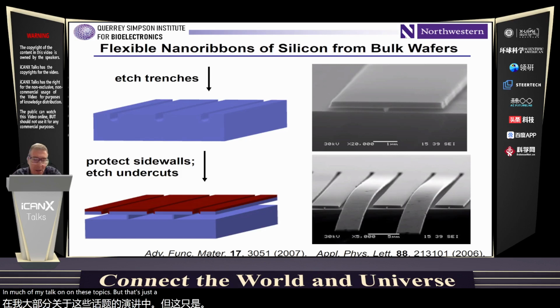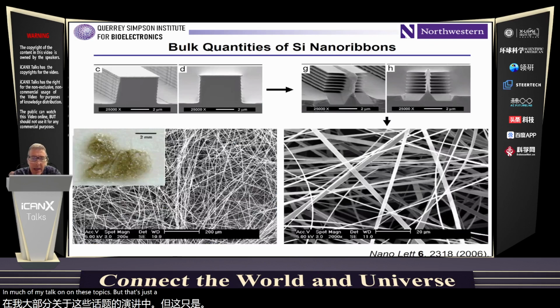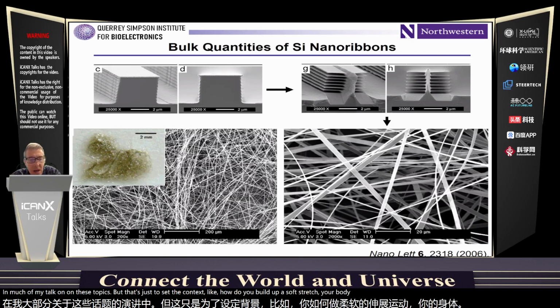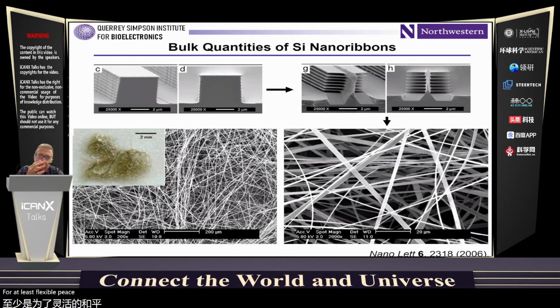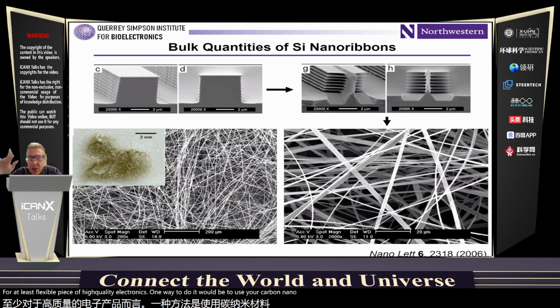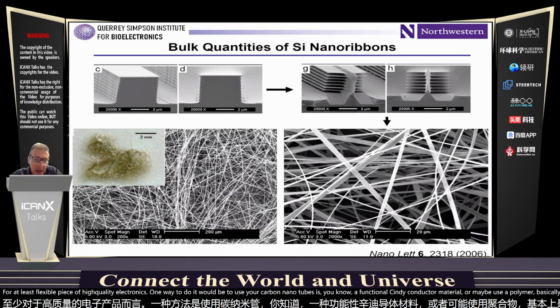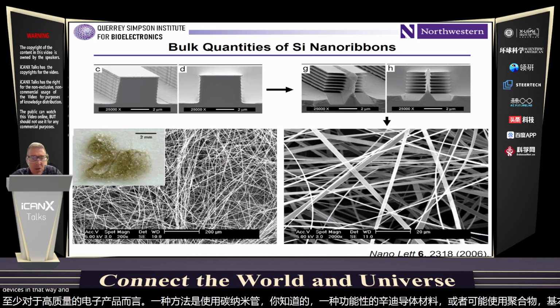And you can work your way down through the thickness of a wafer in a serial sequential set of etching processes, or you can do it in one shot by sculpting the sidewalls of these etched trenches that you develop in the surface of the wafer. These are wafers where you use TMAH or KOH to anisotropically shave these layers off the near surface, and you can do that in multi-layer stacks. Just in terms of throughput, you can create really mass quantities of these materials with semiconductor device grade properties, because they're being derived from wafer-based sources using the most well-developed crystal growth techniques.